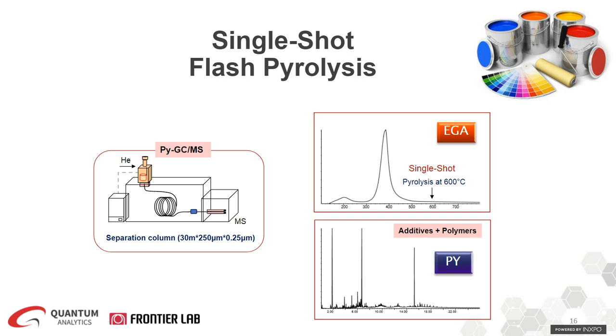So to perform flash pyrolysis, you have to switch the EGA tube to a separation column, and that is shown on the left-hand side. You'll do that switching of the columns by an accessory called GCMS vent-free adapter. This is something that allows you to switch the columns from EGA to separation column or vice versa without actually having to vent your MS and waiting for it to be pumped down. So it saves a lot of time and adds efficiency in your laboratory. Then you program your furnace at 600 C and you obtain a pyrogram. That is a combination of additives and polymers. Again, this is called single shot or the flash pyrolysis.